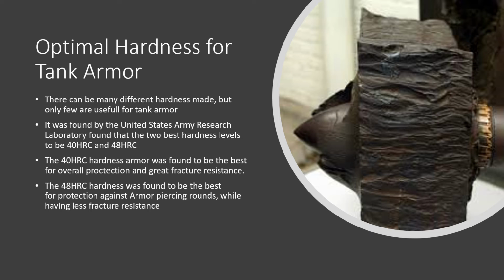The optimal hardness for this tank armor is very important because too hard and it's too brittle, and not hard enough and it won't stop any shells. Now, the United States Army Research Laboratory found that the two best hardness levels were 40 HRC and 48 HRC.